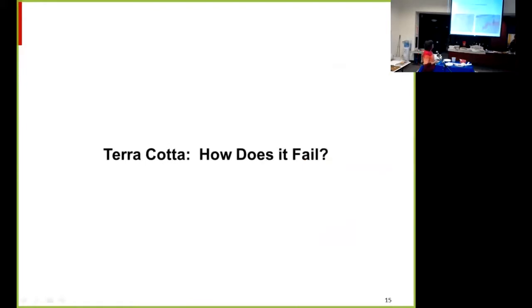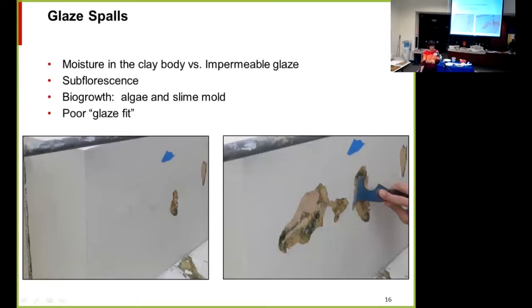So how does it fail? Probably the most common type of failure we see are what we call glaze spalls. And that's where little pieces of glaze start coming off, and then eventually you can lose lots of the glaze of the terracotta. There's a lot of different reasons that you can get glaze spalls. I think the most common one in California is that water gets into the clay bisque somehow through a little crack or open joint or something, and then it's trapped behind the glaze. That is the perfect environment that algae likes to grow in. So you get algae growing underneath the glaze, and then it eats the clay bisque, and then you get slime mold that grows there and eats the algae. And so you have this whole little garden growing under your glaze.